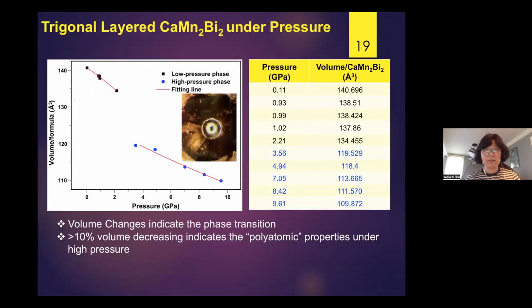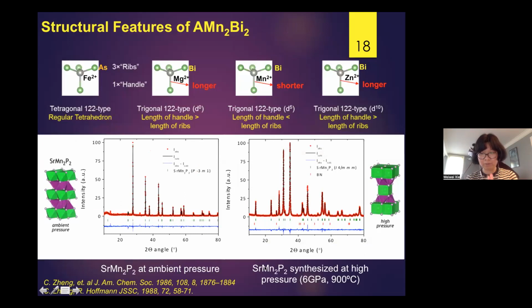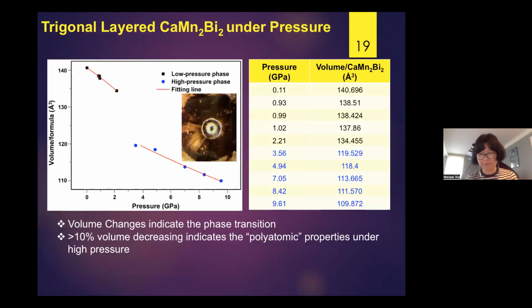Again, we started from a similar 1-2-2 compound, but we used calcium manganese 2 bismuth 2. With high-pressure synthesis, the material is stable at ambient pressure after we treat it at high pressure and high temperature. But to be honest, in the beginning I had no idea how much pressure we needed for a phase transition, so we had to test it one by one. We worked on high-pressure X-ray diffraction to find the phase transition pressure, and we can clearly see the structure change around 2 to 3 GPa.